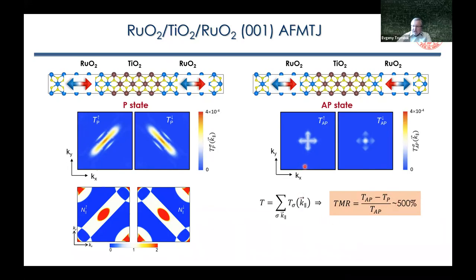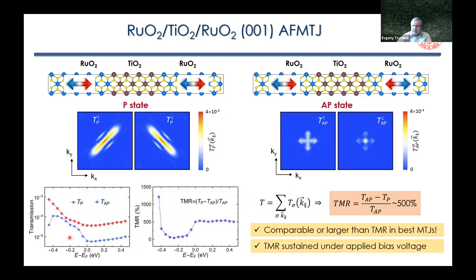So this is a very large effect, which is in fact comparable to or even larger than the tunneling magnetoresistance in the best magnetic tunnel junctions where you're using MgO type electrodes. So this is quite a significant finding, I think. Moreover, this calculation is done at the Fermi energy. So if you apply bias voltage, you dilute the contributions from different energies. So what we did here, we calculated transmission as a function of energy to go away from the Fermi energy, which is sitting at zero, and then calculated the related TMR.